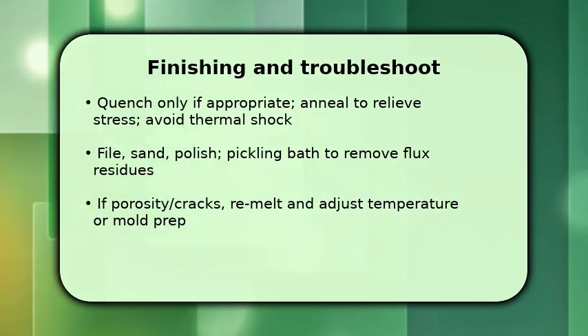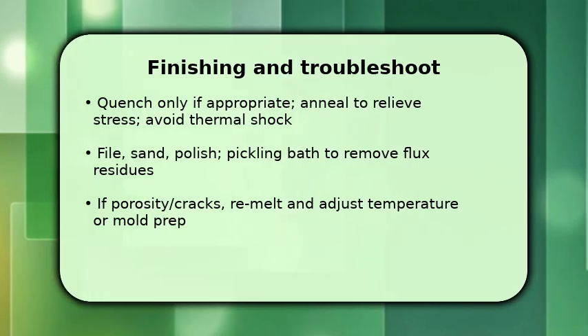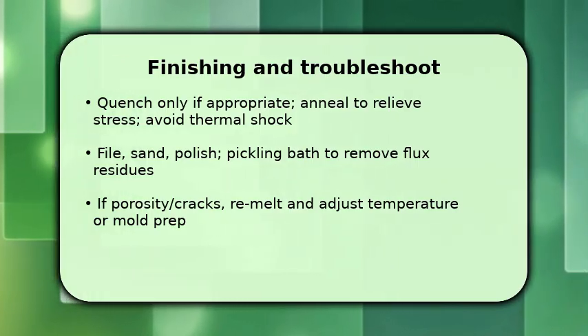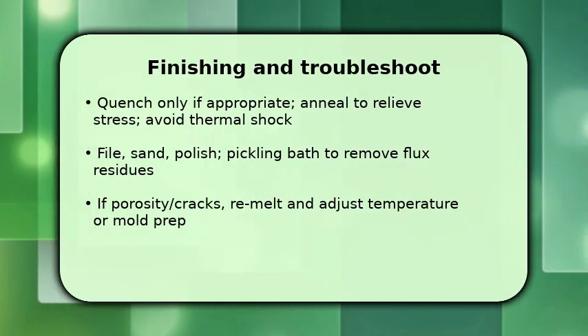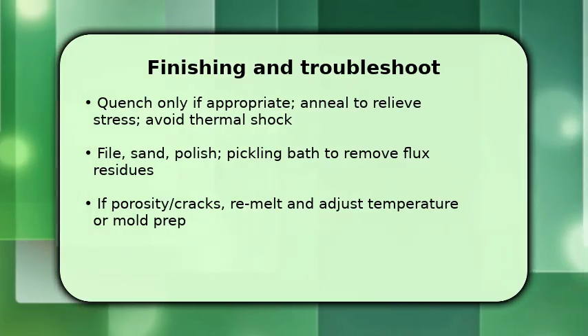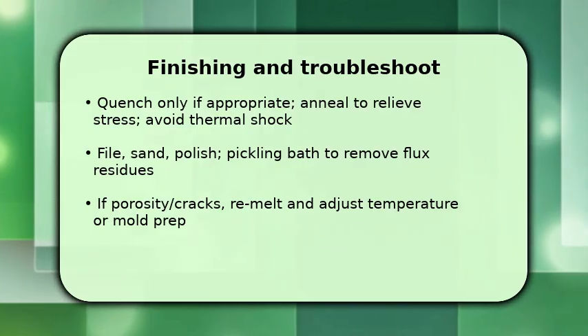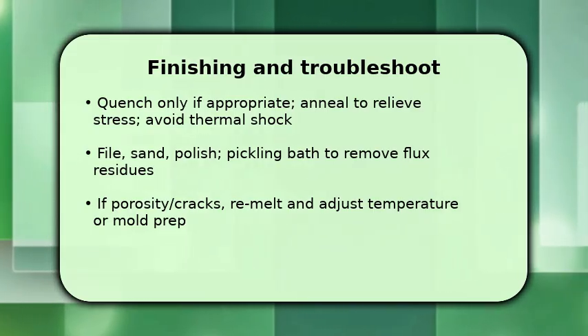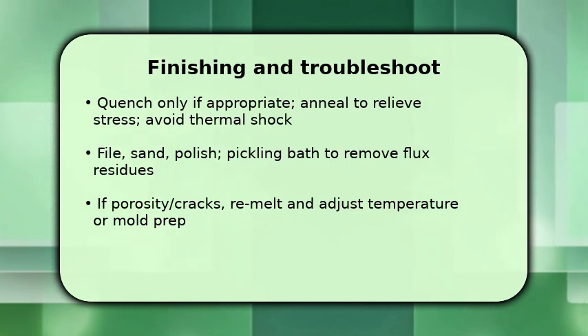If you find porosity, cold shuts, or cracks, re-evaluate. Increase pouring temperature slightly, preheat mold more, improve fluxing, or degas the metal. One key tip: if porosity appears, check for moisture in the mold and dry it thoroughly before retrying.